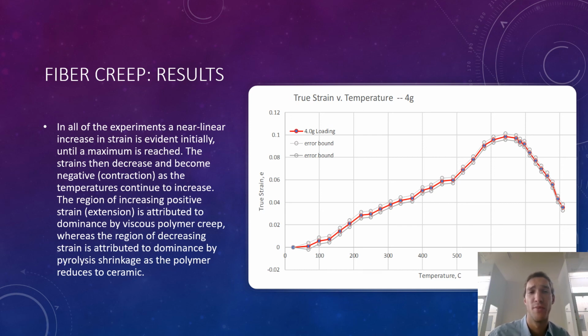You can see from this one graph of the 4 gram loading on these fibers of the true strain versus temperature, it experiences a near linear increase in the strain until a maximum is reached. The strains then decrease and become negative as it contracts due to the reduction into the ceramic. The region of this positive strain, the first section here, the extension, is attributed to the dominance by viscous flow in the polymer. And then, of course, the region of decreasing strain is attributed again to this pyrolysis shrinkage as the polymer is reduced down.